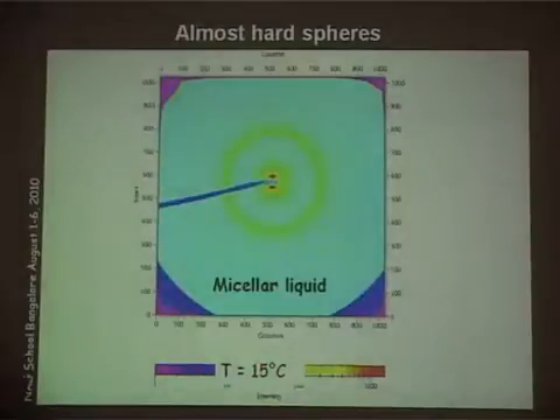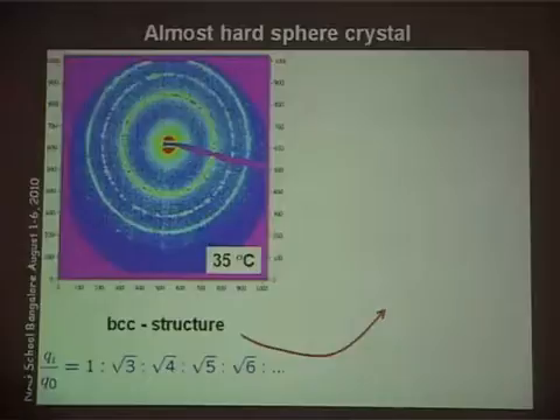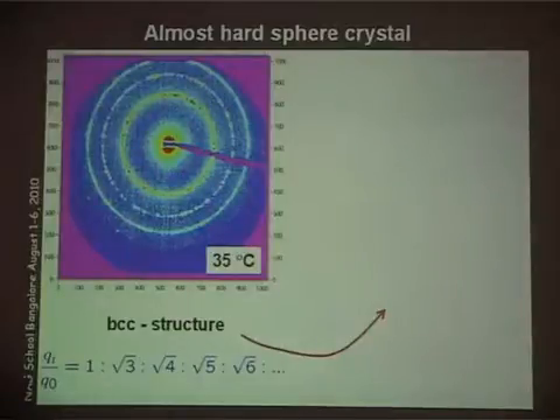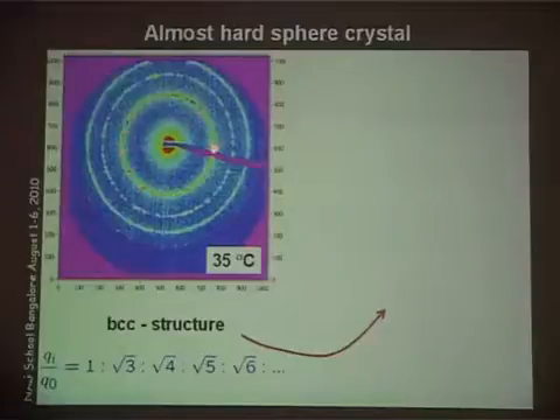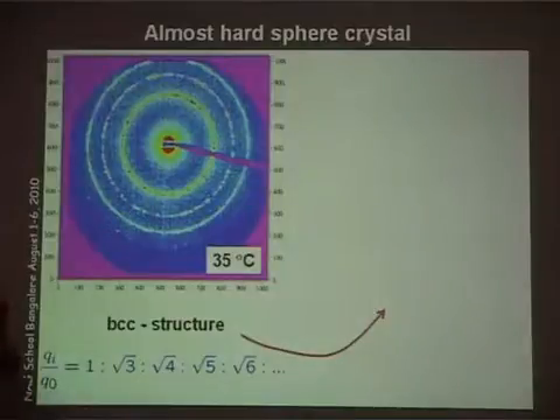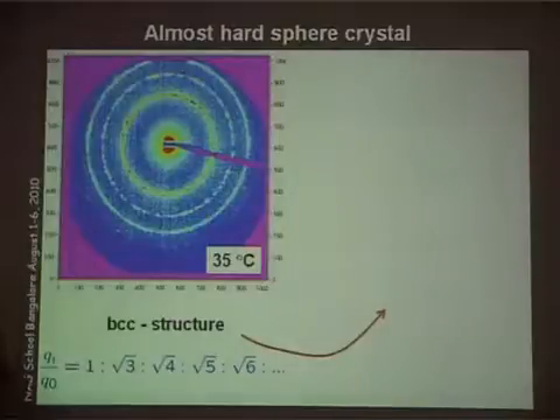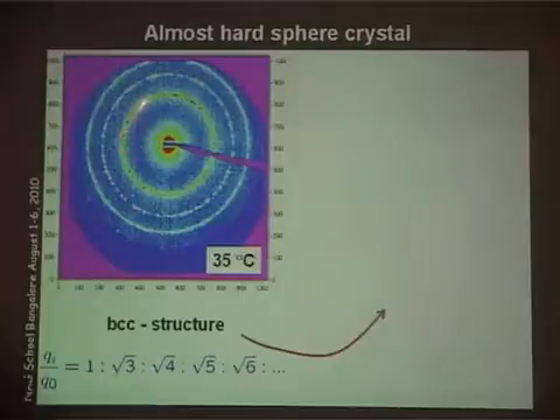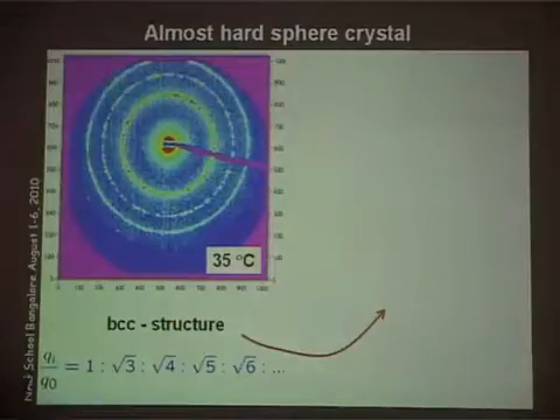Now we heat it up. And that's what you get. Obviously, we went from a totally liquid ring to a very nicely powder crystalline sample. What you see, this graininess here, is that you have formed many little crystals with different orientations. And as I said, if I rotate my sample, the scattered pattern rotates with it. So these are basically powder rings.